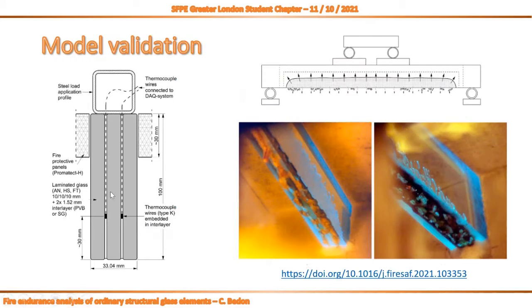And here you see in more detail the experimental setup and the experimental behavior that I was talking about. So 3 layers of glass in a simply supported setup under a mechanical load at the mid-span section. You can see in these pictures, or from the link with more extended discussion, the typical behavior that was experimentally observed. We are talking about glass layers that are sensitive to temperature increase, but also of bonding layers, the interlayers, which are for sure even more sensitive to temperature. And you can see this degradation in the form of bubbles and white regions in the thickness.